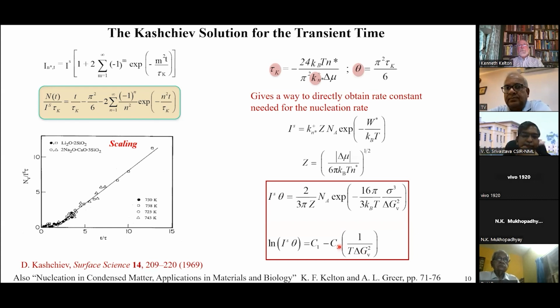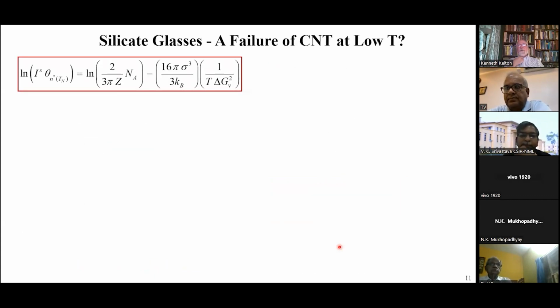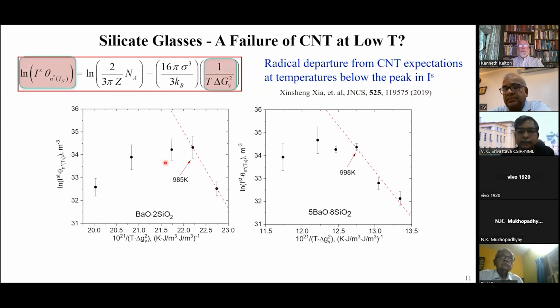And this is one of the reasons I wanted to introduce this, because this has been hearkened and discussed for 40 years, that this points to a failure in the classical theory. Let me explain what that means. So here's that equation I showed you. Here are two different glasses, both barium silicate glasses, but with different stoichiometry.